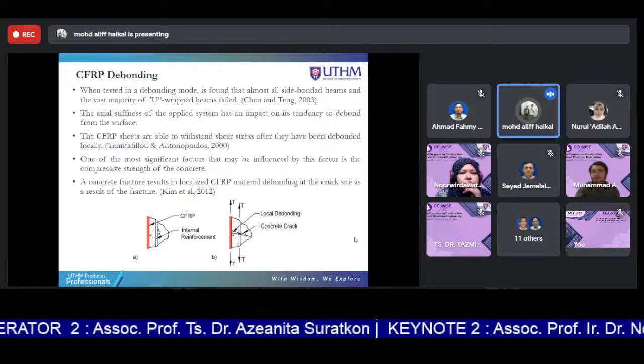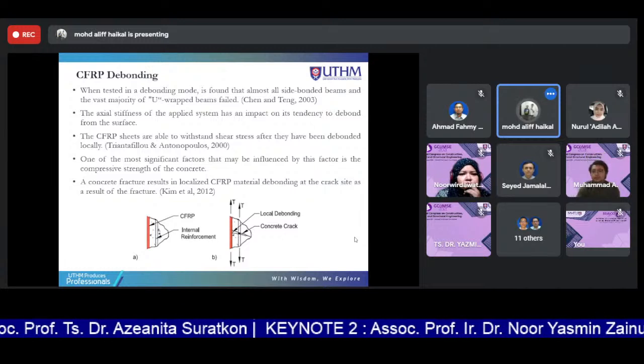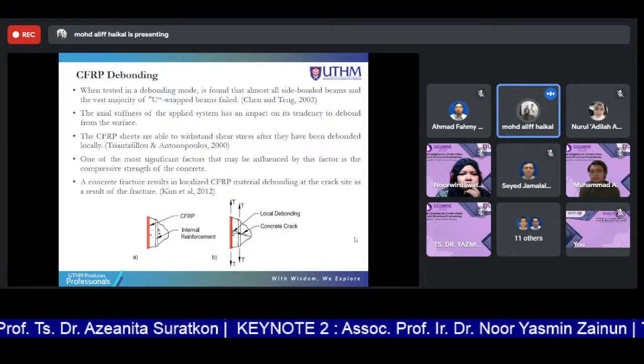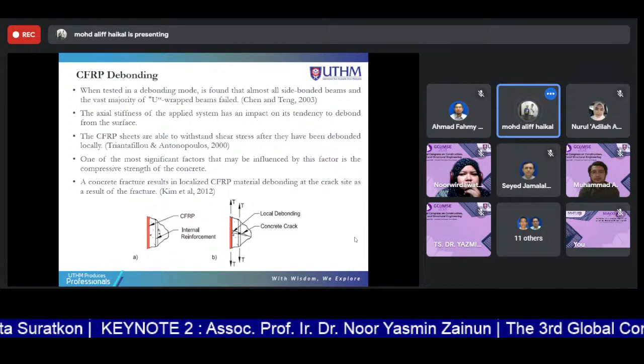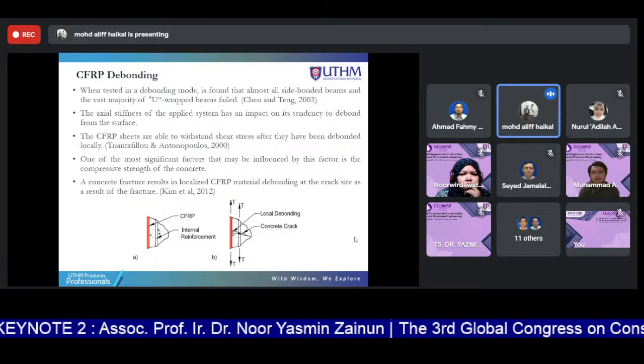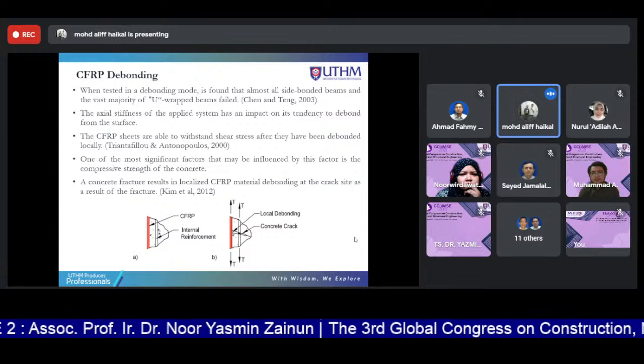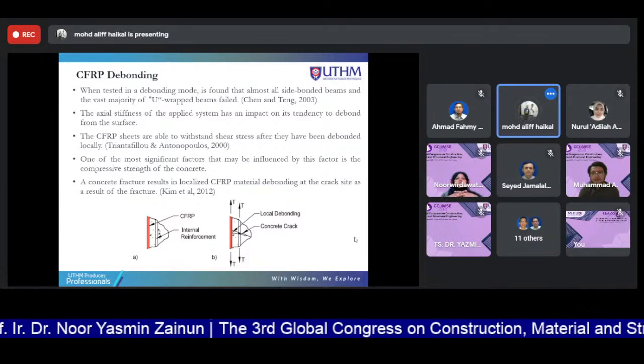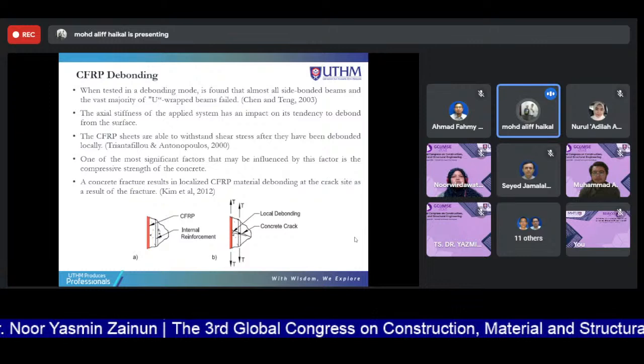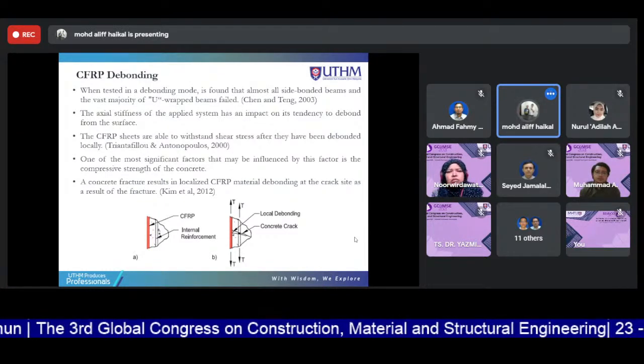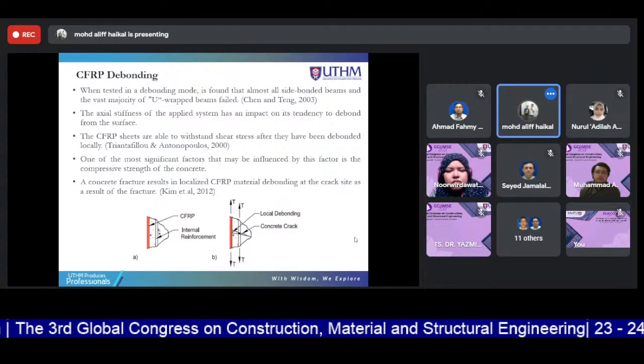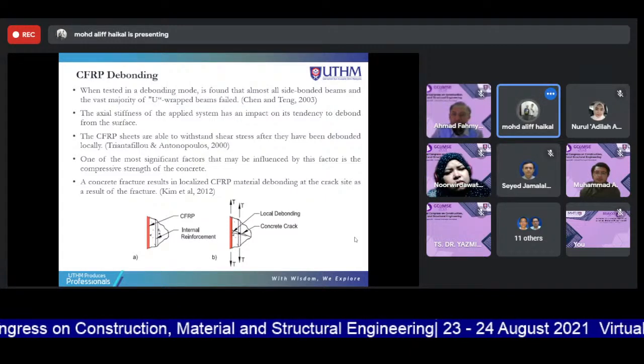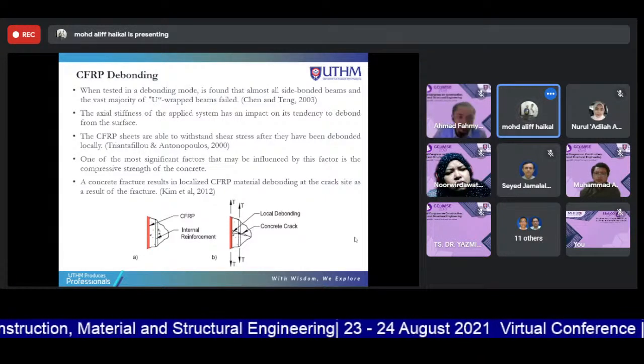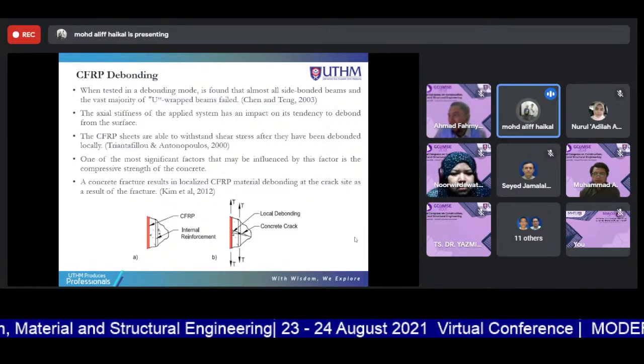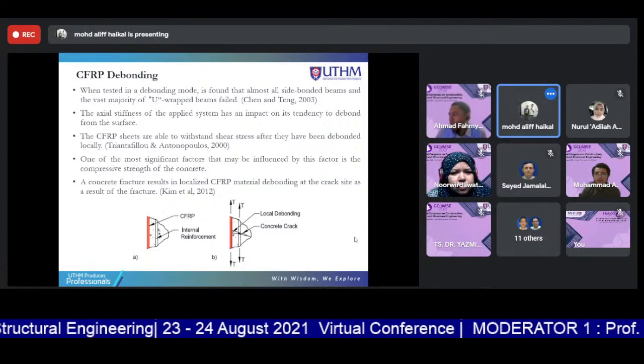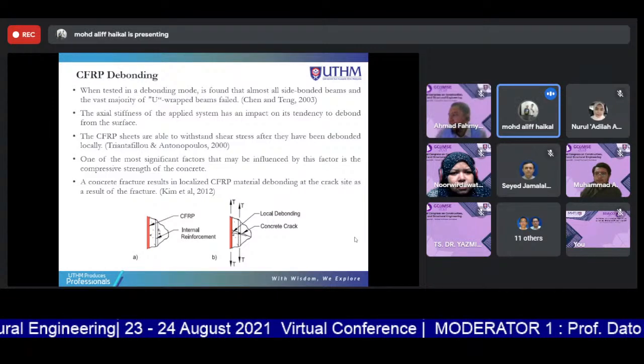CFRP debonding. When tested in debonding mode, it was found that almost all side bonded beams and the vast majority of U-wrap beams failed. The axial stiffness of the applied system has an impact on its tendency to debond from the surface. The CFRP sheets are able to withstand shear stress after they have been debonded locally. One of the most significant factors that may influence this is the compressive strength of the concrete. A concrete fracture results in localized CFRP material debonding at the crack site as a result of the fracture.